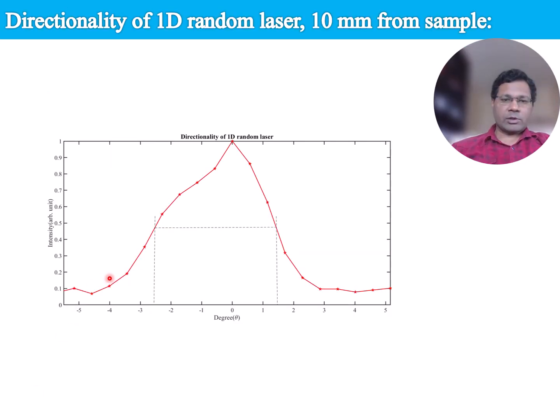We also measure the directional emission of our random laser by measuring the angular distribution of the emitted light. For this we use a 20x microscope objective coupled to a multimode fiber that is connected to the spectrometer to record the spectrum intensity, and this microscope objective is scanned across the cross section of the laser. This collection system is placed at 10 mm from the sample edge and aligned orthogonally to the sample to capture the emission along the lateral direction. From this measurement, we determined that approximately 50% of the total emission is confined within plus minus 2.5 degrees of the central axis, indicating a relatively high degree of directionality.